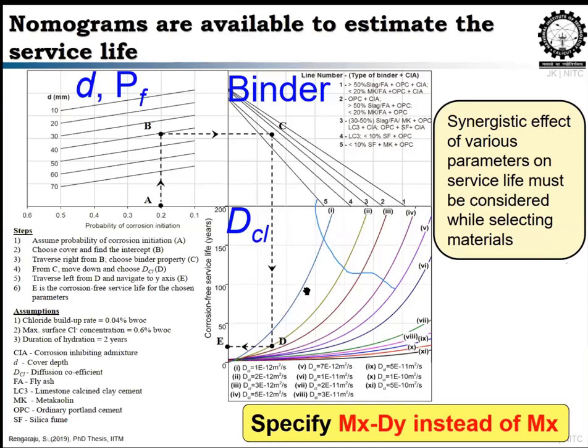If you are picking case 1 as your diffusion coefficient, it is 1 into 10 power minus 12. Then you choose the binder you want. For this case, I'm taking 4. If you move directly towards that, all you need is 50 mm cover to achieve 100 years of service. So based on the quality that you can bring into the site, you can choose your binder, your mix proportion, and your cover depth. And as we don't have the option to choose the cover depth, the cover depth will be fixed as an independent parameter, and the dependent parameters will be modified for your requirement.